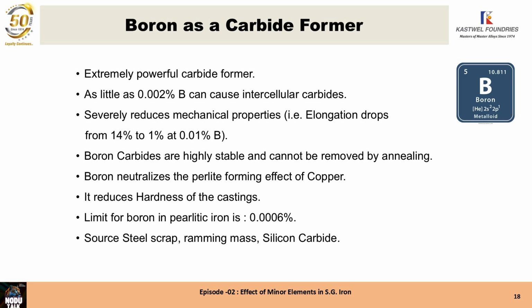Boron is a carbide former. It's an extremely powerful carbide former. As little as 0.002% boron can cause intercellular carbides. It severely reduces the mechanical properties. The elongation drops from about 14% to 1% at 0.01% boron. Can you imagine? Elongation of S.G. iron dropping from 14% to as low as 1% at 0.01% boron. Boron carbides are highly stable and cannot be removed by annealing.